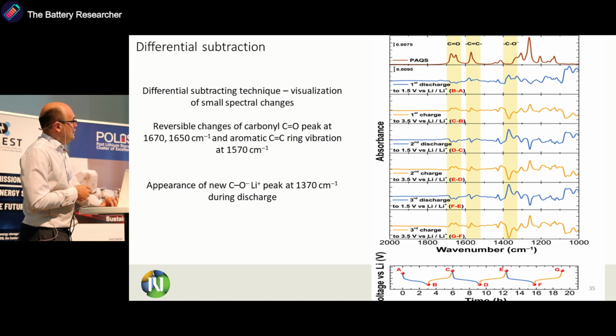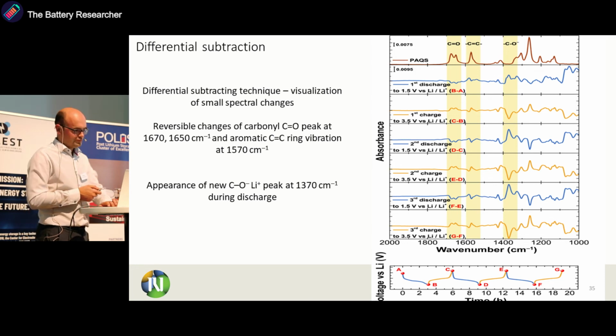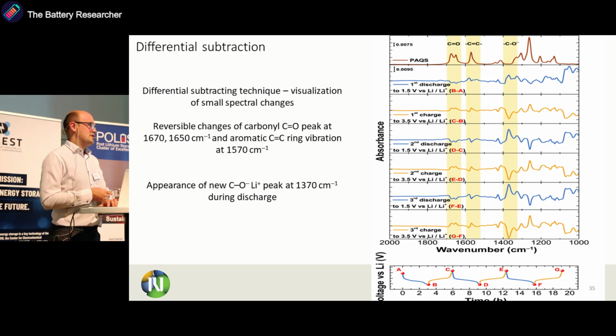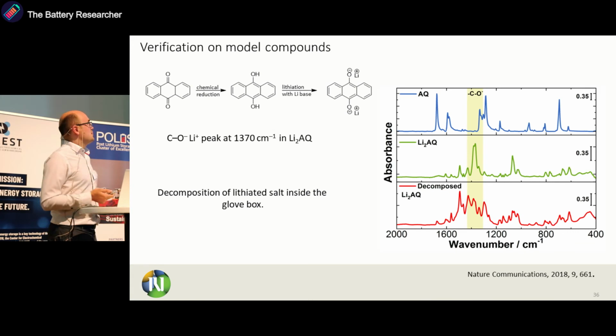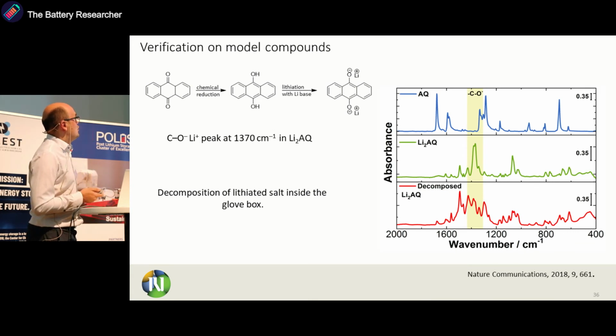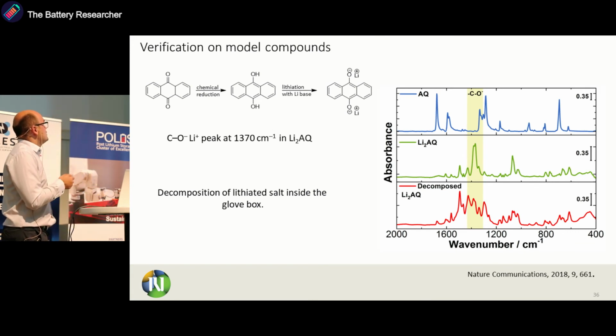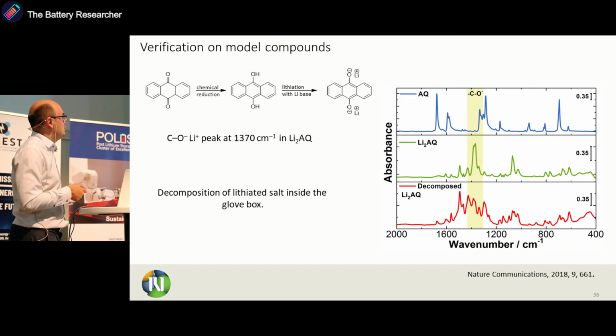Additionally, we have here new bands appearing between 1100 and 1000. So this is quite useful because then you can see basically all the infrared active changes during your cycling. To confirm this, we also synthesized model compounds. We reduced anthraquinone to OH groups and then reacted them with lithium base to get this sample. And here we're clearly able to see this strong peak at 1370 connected with CO minus lithium.